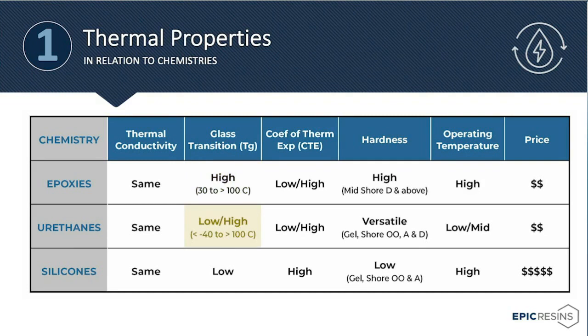Urethanes have more versatility. Because of the raw materials that are available to us, we can make urethanes with low glass transition temperatures and high glass transition temperatures. Silicones, on the other hand, generally have lower cross-link density, so they're going to have lower glass transition temperatures. So when we compare these three chemistries for coefficient of thermal expansion, epoxies can have both low and high coefficients of thermal expansion. And this is based on, number one, the types of filler that we use, as well as the cross-link density.